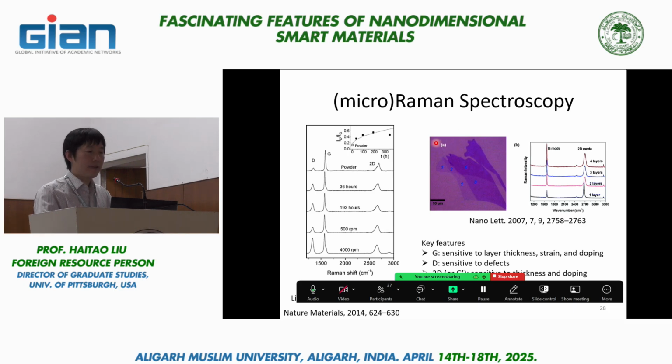In the case of graphene research, people often use oxide thickness around 280 nanometer, and that turns out to be a thickness that can enhance the optical contrast of graphene, and by the same reason, enhance the Raman response of graphene. So for graphene samples deposited on those kinds of substrate, you can produce a pretty strong Raman signal by using Raman laser intensity as low as a milliwatt or so.